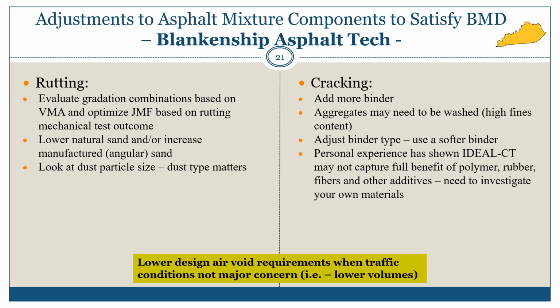He found dust affecting the binder to be a contributing factor to some cracking issues. He recommended looking at adjusting the binder type. Try using a softer asphalt binder to help reduce the stiffness of the mix. And one of the things that he did say was that in his personal experience, the IDEAL-CT test may not capture the full benefit of polymer modified binders. That needs to be considered and taken a look at when running that particular test for modified asphalts.